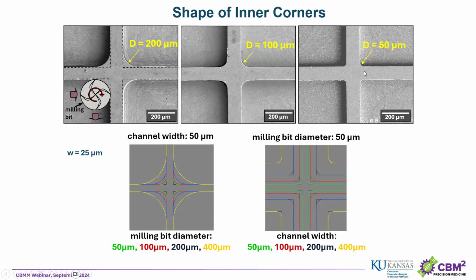And of course, you can minimize it by using smaller bits. And also, if you're using larger channels, the appearance of this curvature may be completely different, right? And here we can see in those two pictures below that if you cut a 50 micrometer channel, you can see how bad this 400 micrometer bit would look. But if you try to cut a 400 micrometer channel, that would be much less pronounced.